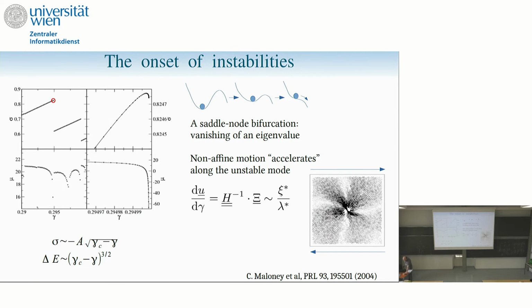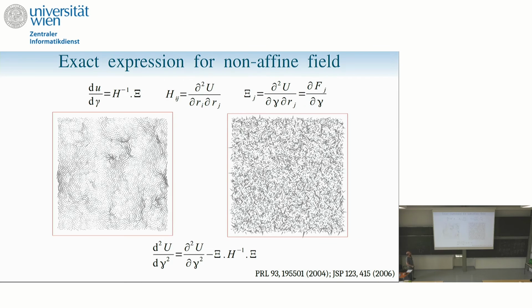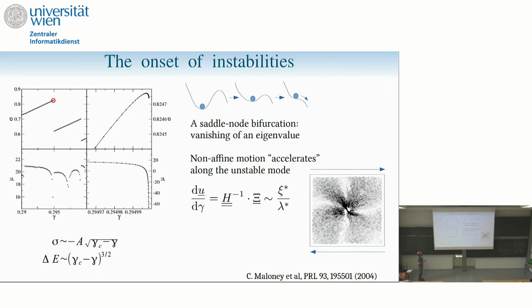Okay, so now we have looked at the elastic response, and we are progressively going towards plasticity. So again, plasticity occurs because, I just have here the same sketch as before, the system is in a local minimum, and then you reach a local instability, and this instability is a saddle node bifurcation. Here it's a saddle node in the sense that you have this local minimum, and at some point between these two points, the system is flat, and it means that you have locally one eigenvalue which is 0.